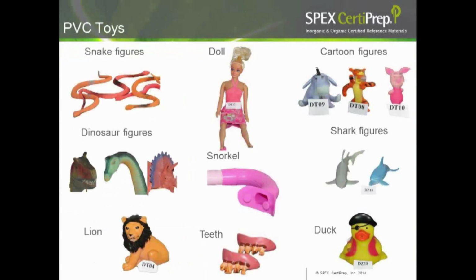Since PVC toys are notoriously very dirty with organic contaminants like phthalates, we thought this would be the best place to start looking for heavy metal contaminants. So some of our PVC toys turned out to be some of these dinosaur figures, our friend the rubber duck, the teeth, and the snorkel. The teeth and the snorkel were of particular interest because they're meant to be put in the mouth. We also had some cartoon figures that we've blurred out the identities of to protect the innocent.